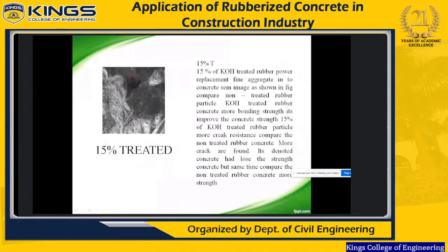So what do we mean by treated rubber? Wherever the raw rubber is crusher powder, for example 30 mesh, it is washed a little with water and dried. Oven drying is not required, normal drying is enough. After that it is mixed with the concrete and we make it for testing; this is non-treated rubber. Treated rubber means we immerse it in the KOH solution, take the rubber from that and make it for the study, which is called treated rubber.